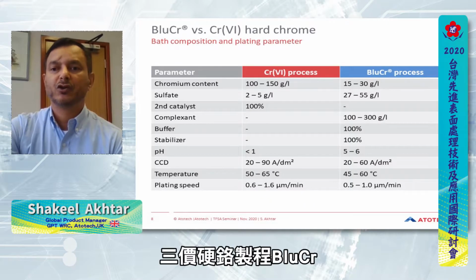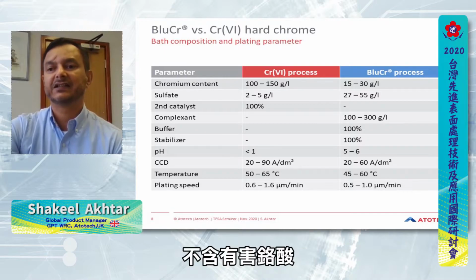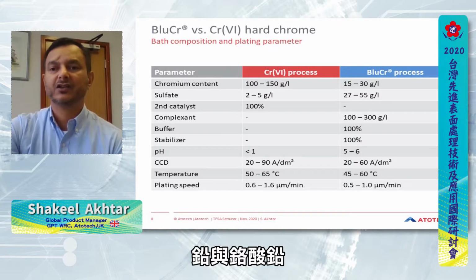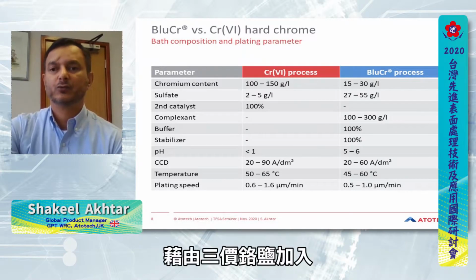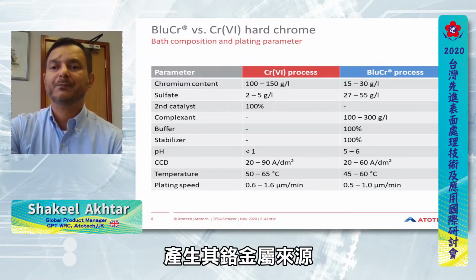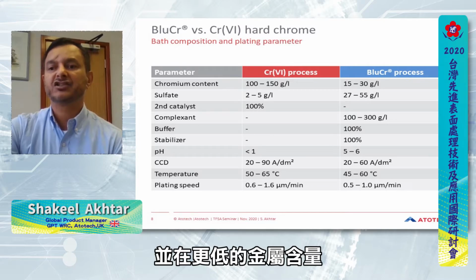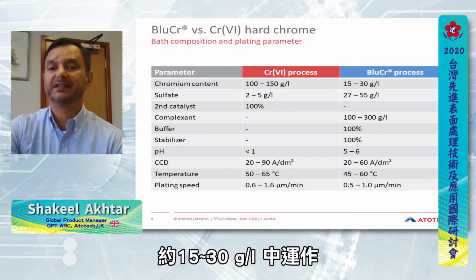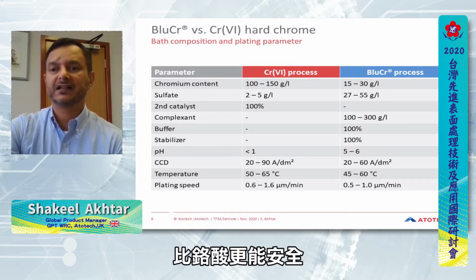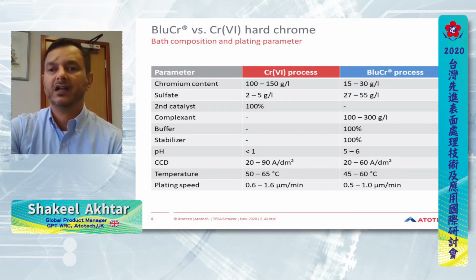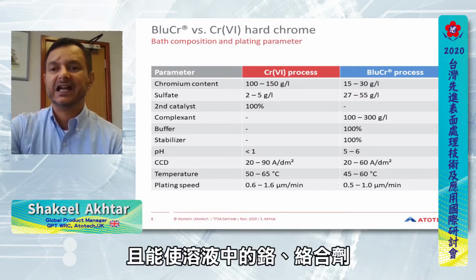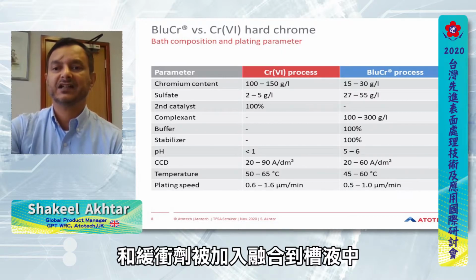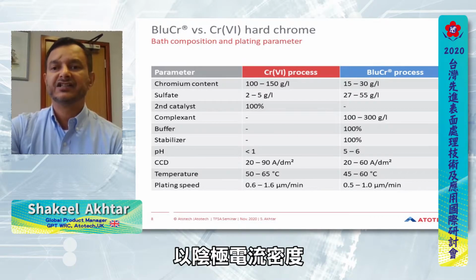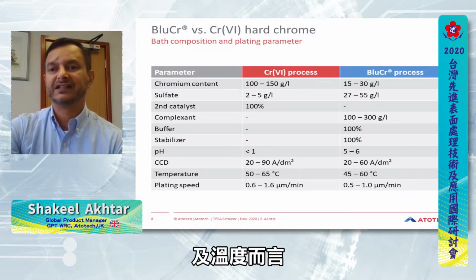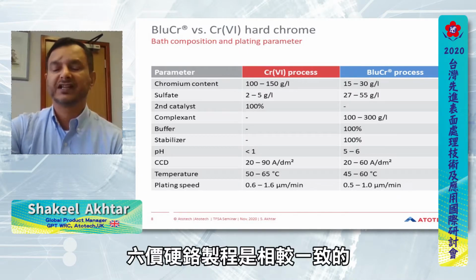As mentioned earlier, the blue chrome trivalent process does not contain the hazardous chromic acid, lead and lead chromate, or the PFAS fluorinated surfactants. The chromium is added to the bath via the chromium-3 salts and operates at a much lower metal content of 15 to 30 gram per liter. The chrome-3 salts are much safer to handle and are more environmentally friendly compared to chromic acid. The pH of the process is less acidic, and to keep the chrome in solution under these conditions, complexants and buffering agents are added in the bath. The operating condition of the blue chrome in terms of cathode current density and temperature are comparable to hexavalent processes.